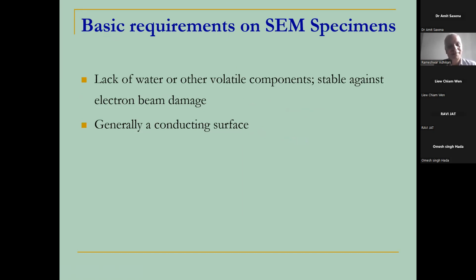Also, for the scanning electron microscope there should generally be a vacuum, and there should be no water and volatile substances. And the specimen should be stable against electron beam damage because we are utilizing very high energy primary electrons, which will be interacting directly with the specimen surface. And the surface should be conductive, generally. I'm not talking about all the conducting polymers, which can be utilized without doing anything most of the time, but not always, because they can also be damaged. Otherwise, we have to make the sample not charging and conducting.